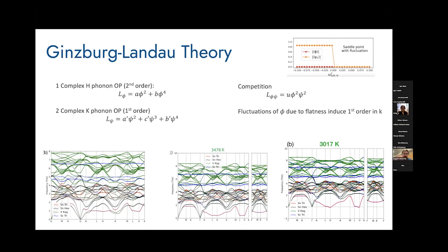But we know that the real CDW is at momentum K bar, which is 1/3, 1/3, 1/3. So what's the scenario? And this is a scenario, of course, because we cannot exactly know what happens, but it's a consistent scenario where that can happen. So why would it appear at a different wave vector? Well, the H phonon, if you write it in Ginzburg-Landau, has an order parameter that has no cubic term. So it's going to have a second order phase transition. But the K phonon, because of momentum conservation, can have a cubic term. This is related to the fact that adding three 1/2 momenta in the z direction does not give you momentum 0, but adding three 1/3 momenta in the z direction can give you momentum 0. So the complex phonon at K, the 1/3, 1/3, 1/3, can have a cubic term, and it would have a first order phase transition.